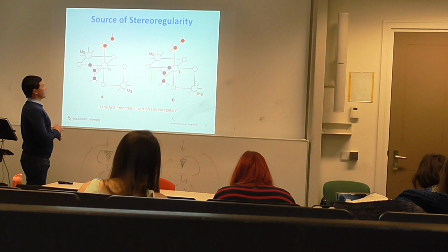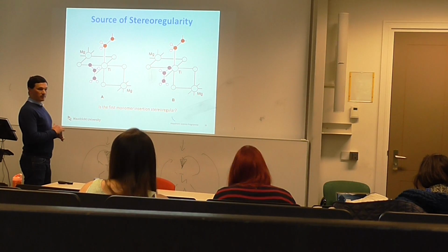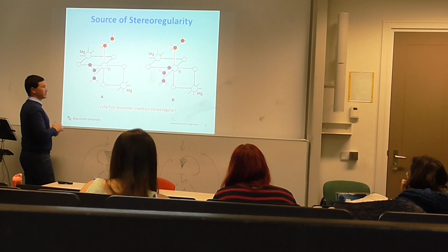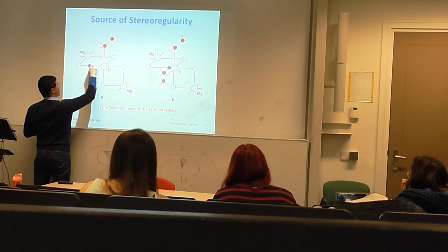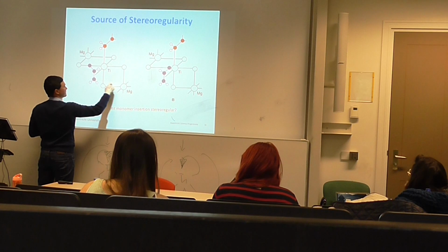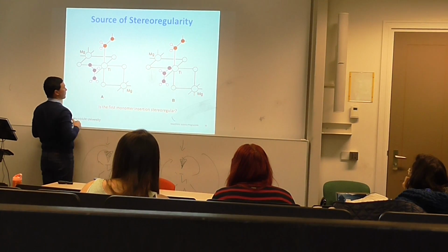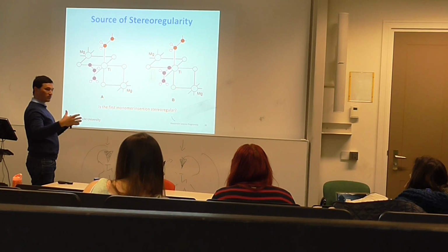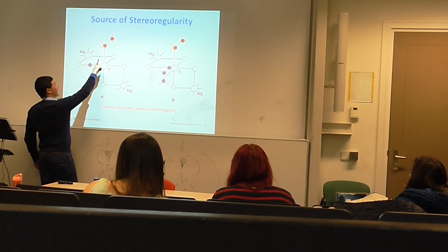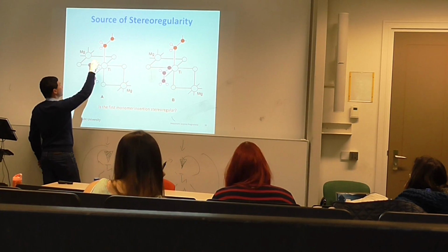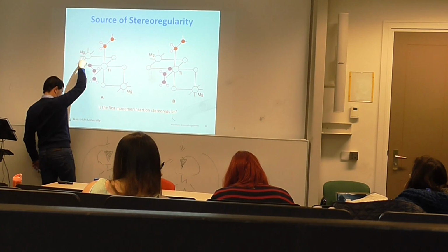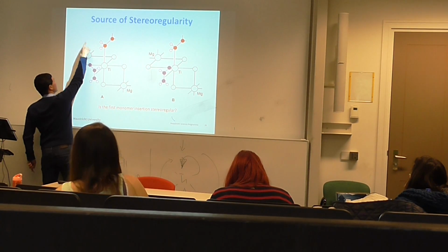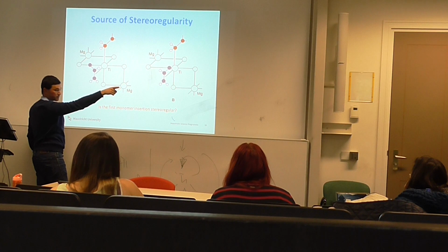So how is this transferred to the monomer? This is more or less the same representation. So you have your metal, your chlorine connected to the magnesium. So this is your bidentate ligand, this is your bidentate ligand. Once the polymeric chain starts growing, it becomes quite big. So it has to point in one direction, right or left. So here, there will be something, chlorine, or we will see later on a donor, which means that this group here will point the chain in one direction. Okay?